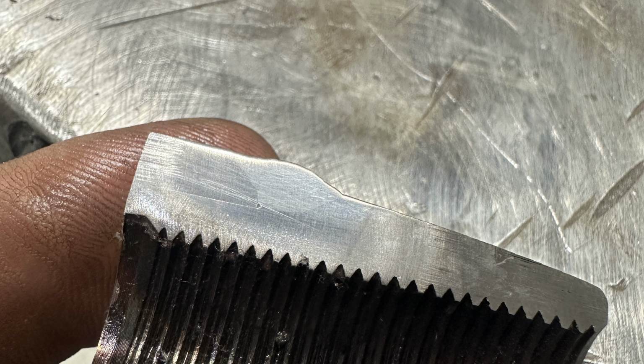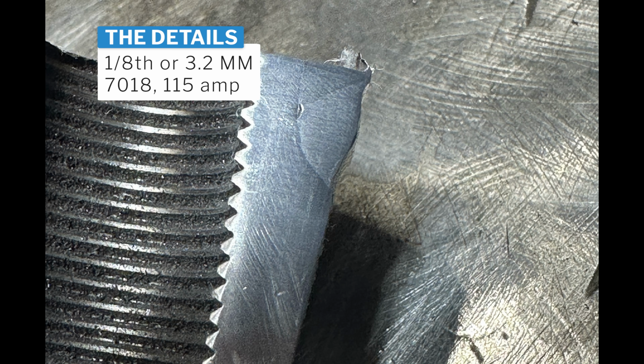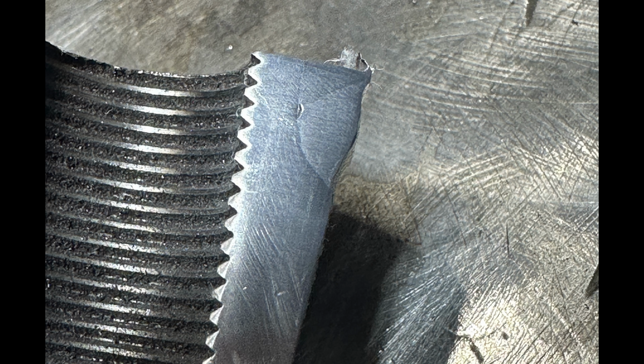Let's look at 115 amp pass with 1/8 inch rods and see how that looks. This also has pretty good sidewall fusion and overall acceptable bead profile, and the lack of fusion at the bottom is a bit worse than running at 130 amps. Now keep in mind, your machine at 130 might be like 150. So my machine I know to be pretty accurate, or at least the machine I use to weld this. So 130 definitely is going to be 130.